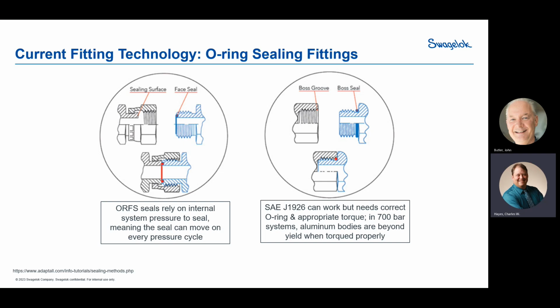The aluminum can be either under torqued, and that's a problem, or over torqued, which is more often a problem, where the aluminum actually stretches in the threads, and eventually when it relaxes, you lose the preload and it backs out. When they back out at 1,000 pressure cycles almost every time, they back out far enough that the O-ring comes squirting out up at the shoulder. When we first started trying to understand that problem, we thought we had an O-ring problem. It wasn't an O-ring problem. We gave the O-ring enough room to get out. It's a gap problem, and it was an issue of losing preload.